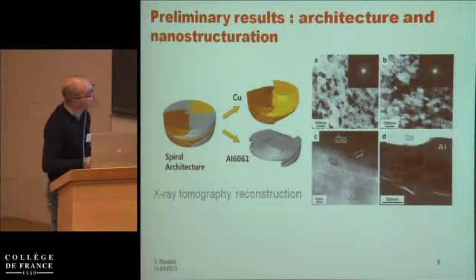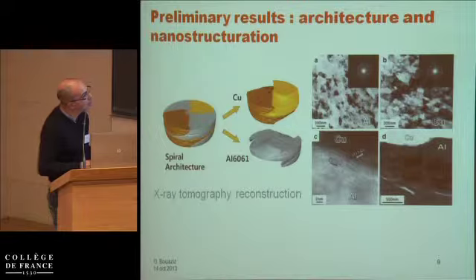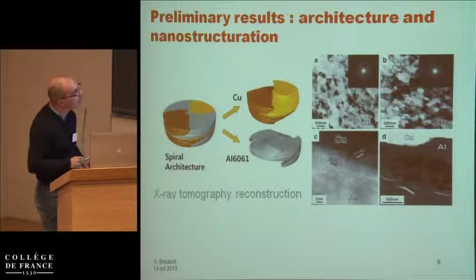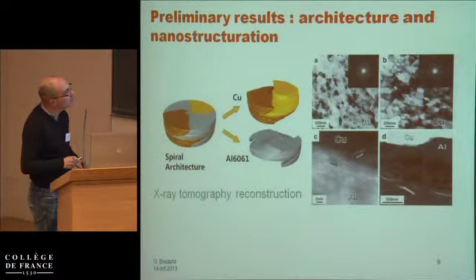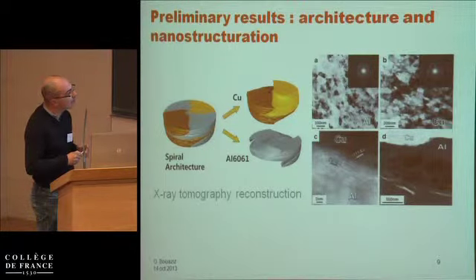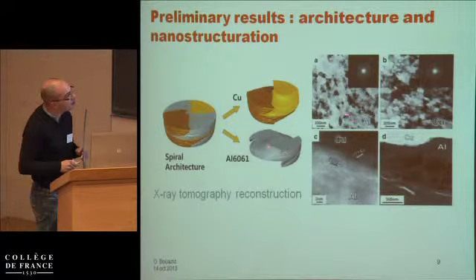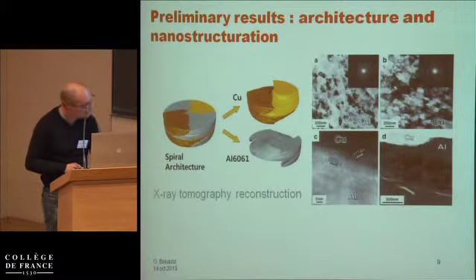But at the same time, we have not only this architecture, but also grain size refinement due to the high plastic strain involved in the process. We have a grain size of the order of 100 nanometers. So in this example, I have shown that using the SPD technique and a special geometrical arrangement at the beginning, you can have architecture at the millimeter scale, but at the same time, you can now structure each material involved in the experiment.